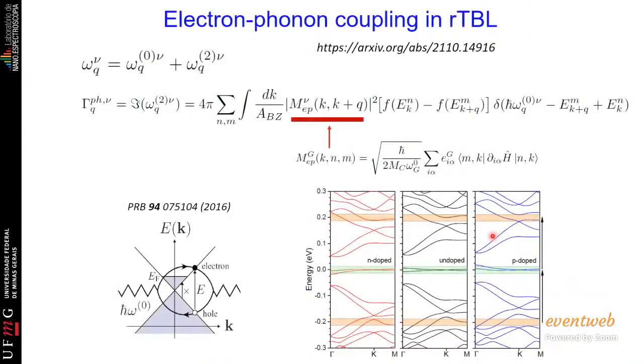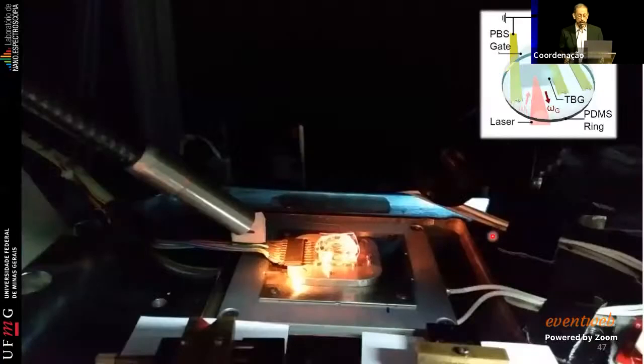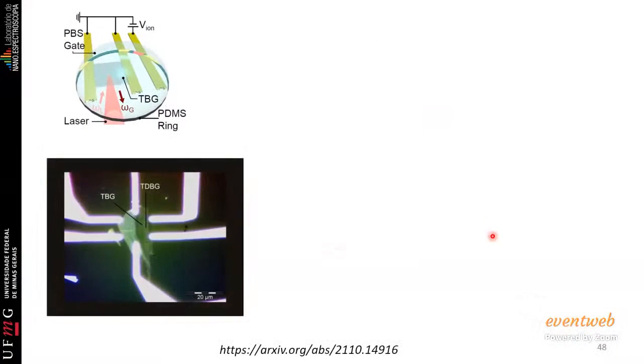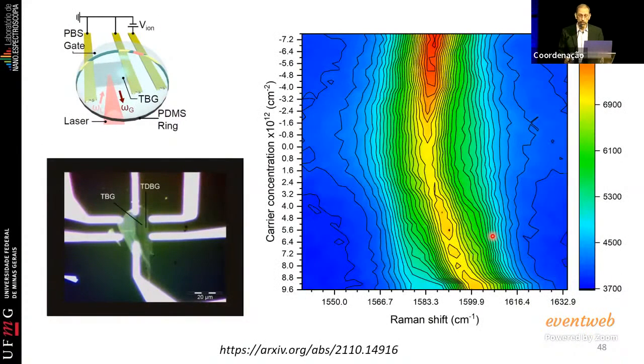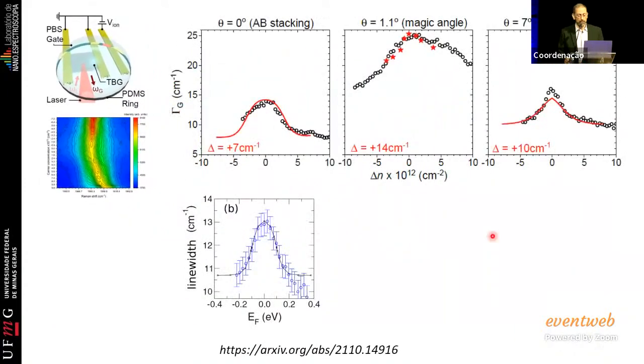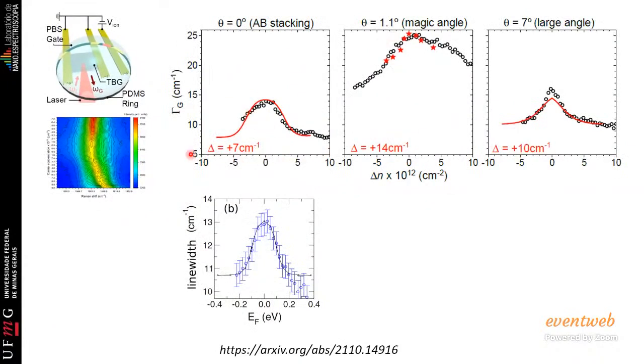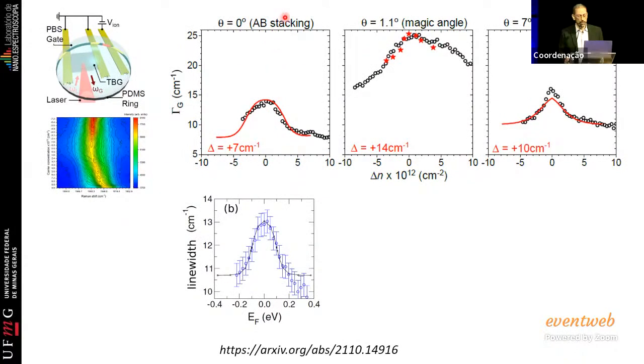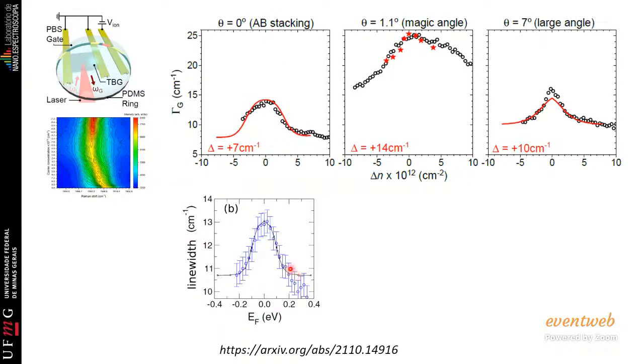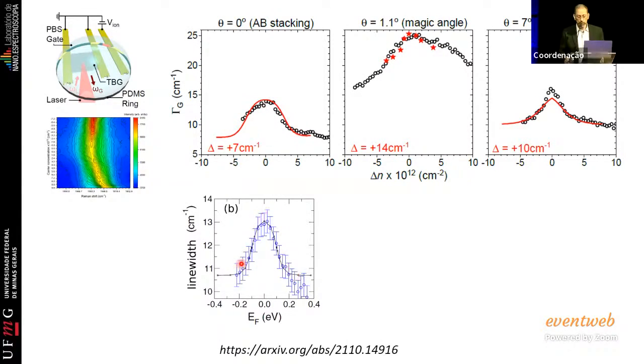And I will skip the theoretical aspect, okay, that is, again, atomistic calculations, and you build a device, on the magic angle or not at the magic angle, you measure the G-band, and you plot what happens with the G-band with gate, okay? So if you do it on the AB stacking, you see exactly the same shape that has been seen a lot. If you do it on large angle, you see something quite similar. But if you do it at magic angle, the behavior is very different: first, the width is much larger, and second, it doesn't decay as fast as this one decays.